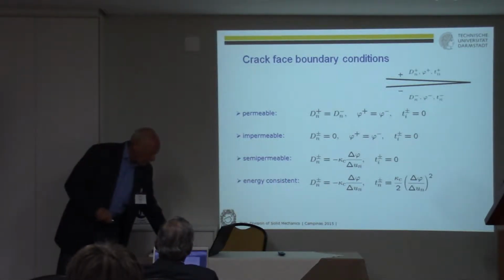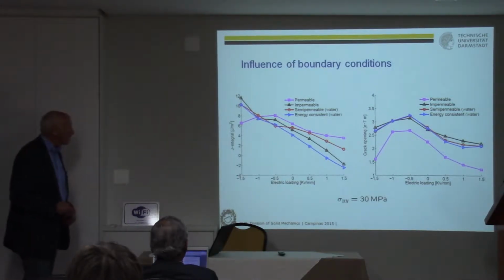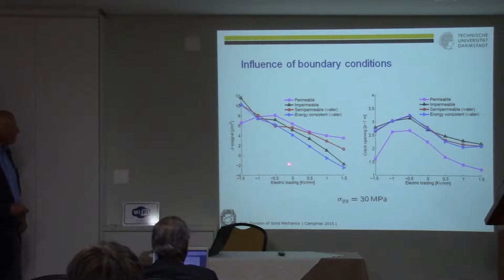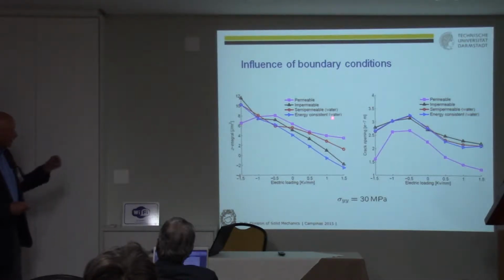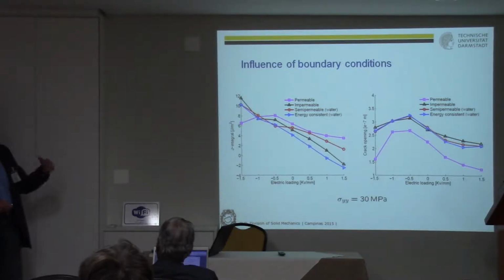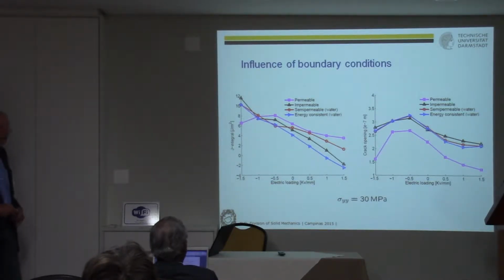And simulation can be done for all these boundary conditions, of course, but then you also need, again, material properties. And here you see the driving force versus electrical loading for different boundary conditions: permeable, impermeable, semi-permeable, energy consistent, where the parameter kappa, which was on the foregoing slide, was taken for water. This means an environment where the humidity is very high, which really can appear.